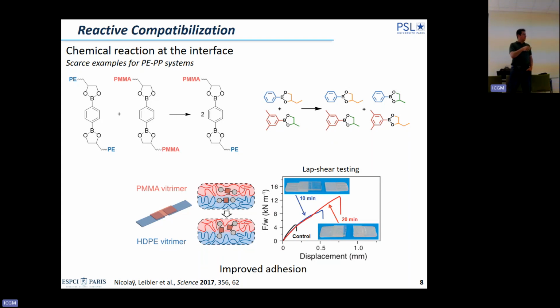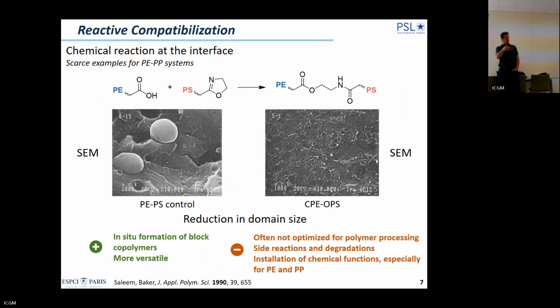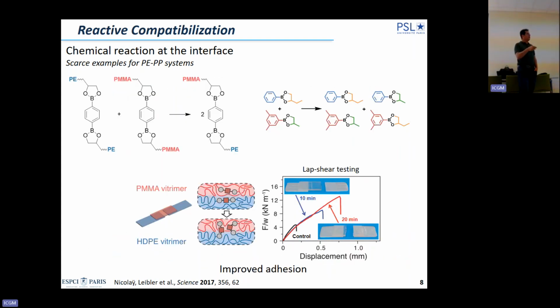So what we did, really linked to this, we made a PE which was cross-linked with this type of function, dioxaborolane. And what is very interesting with dioxaborolane is that if you take two dioxaborolanes, they can undergo a metathesis reaction to reshuffle the partners. So you can exchange the partner which is linked to the bond with the partner which is linked to the diol part, and you make a blend of this molecule.